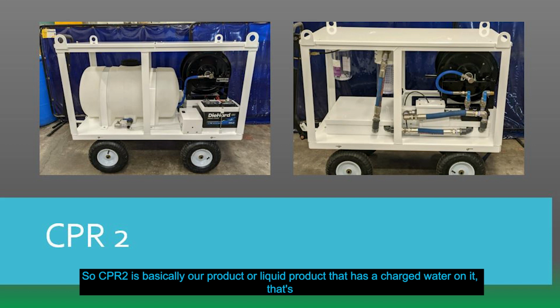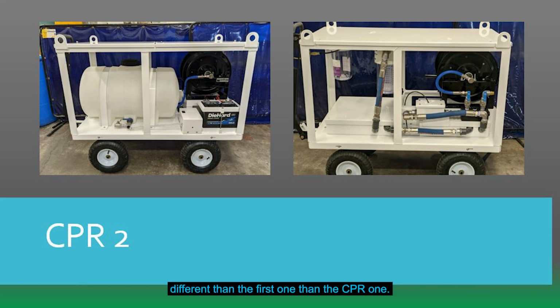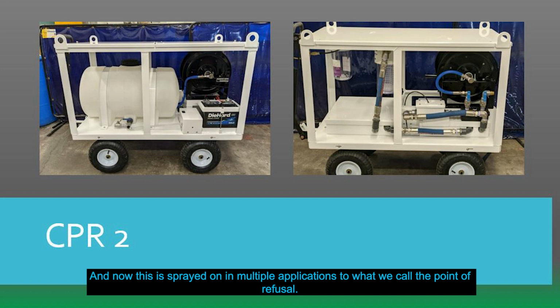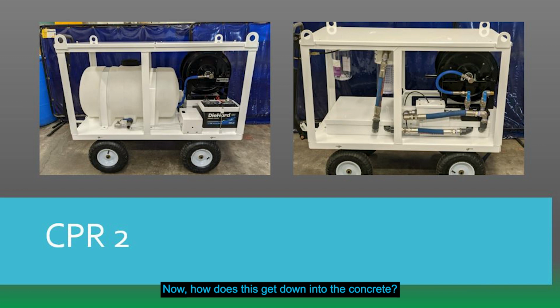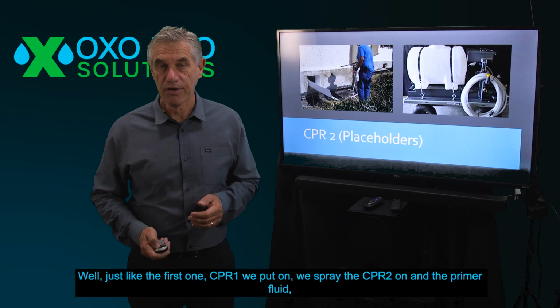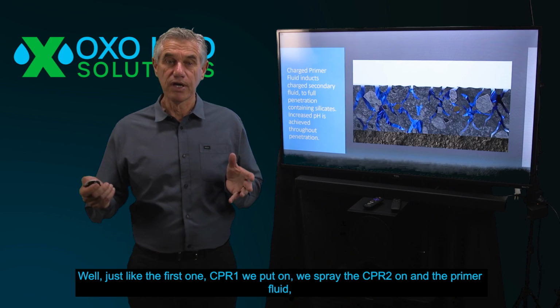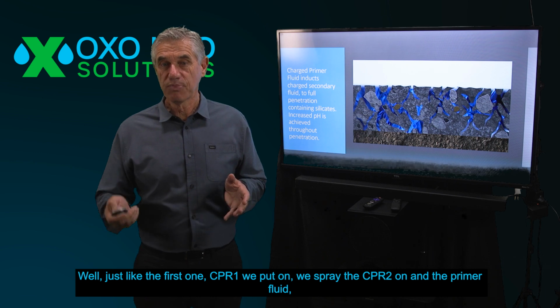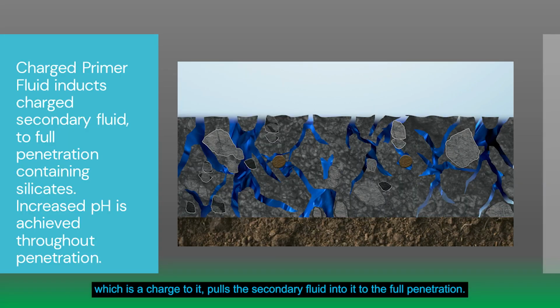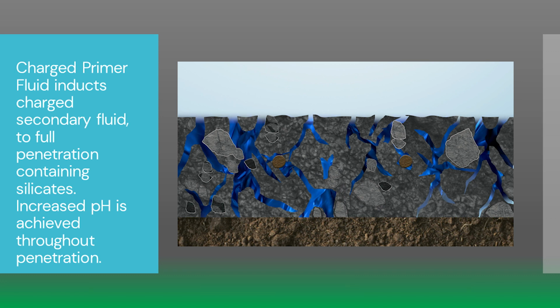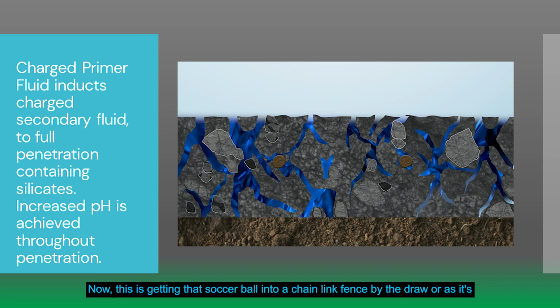So, CPR2 is basically our product or liquid product that has a charged water on it that's different than the first one, than the CPR1. And now this is sprayed on in multiple applications to what we call the point of refusal. Now, how does this get down into the concrete? Well, just like the first one, CPR1 we put on, we spray the CPR2 on, and the primer fluid, which is a charge to it, pulls the secondary fluid into it to the full penetration, and this contains the silicates. Now this is getting that soccer ball into a chain link fence by the draw, or as it's pulling it, it's actually able to squeeze it in and pull it into the full depths.